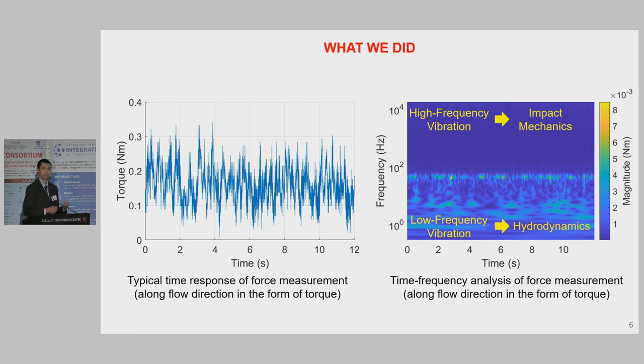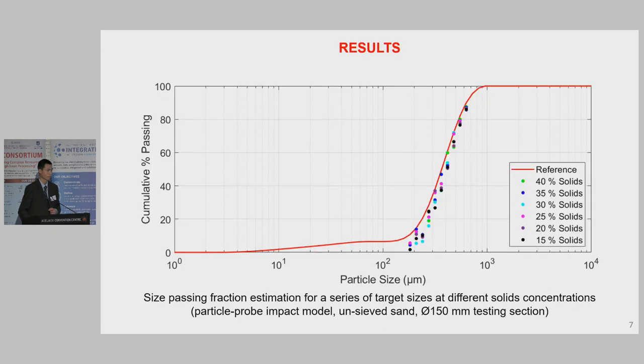But for high-frequency vibrations, we use impact mechanics to interpret the particle probe impact event to reveal the signature frequency associated with different size distributions. Now, the red curve shows the cumulative percent passing of the sample we use in experiments, which is done by laser diffraction method offline with a residual error of less than 1%. So we use it as a reference.